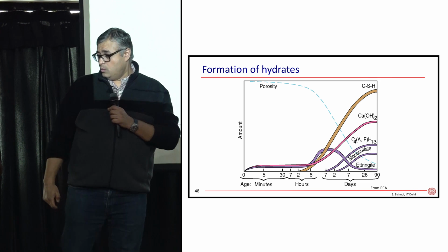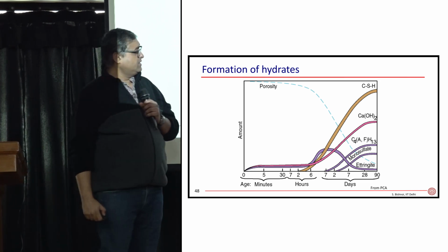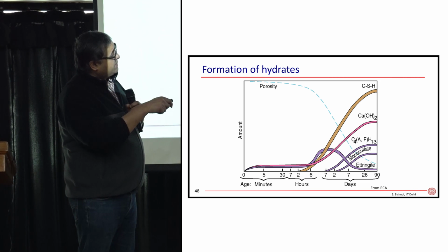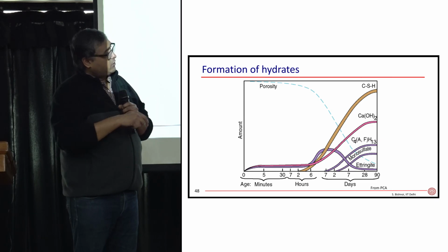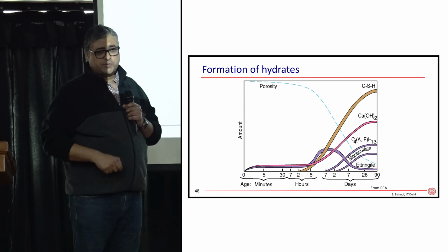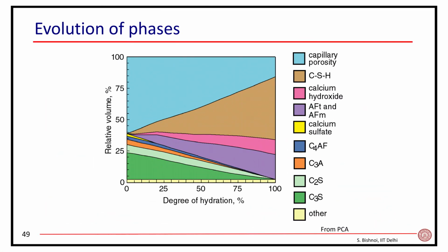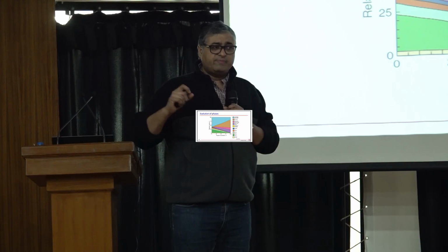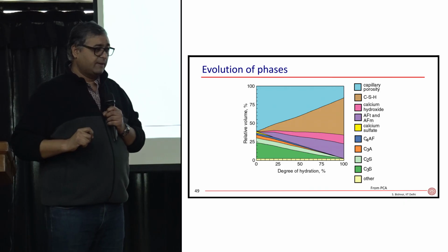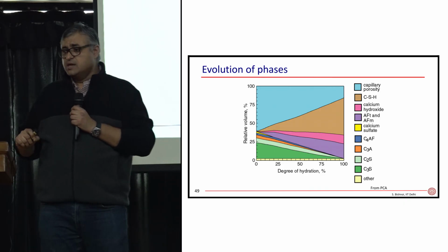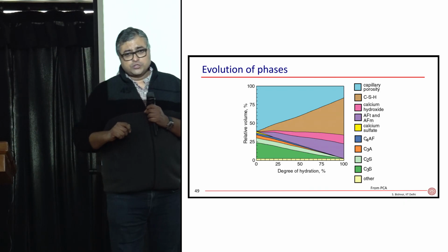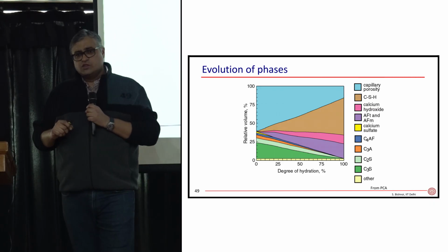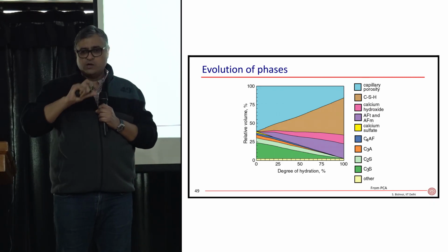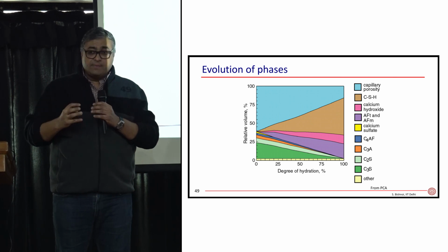Now, while all of these materials are reacting, these products are being produced at the same time. Calcium hydroxide gets produced, calcium silicate hydrate gets produced, ettringite gets produced. But the important thing is that the volume of these products that are produced from the reaction is more than the volume of the reactants that were reacting. If alite reacted to produce CSH and CH, the volume of CSH and CH is more than the volume of the alite that reacted. So you end up having more solid.